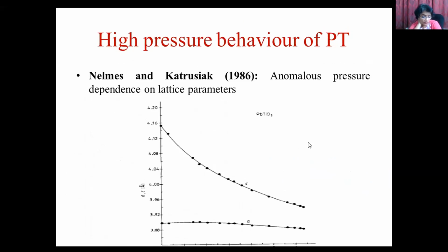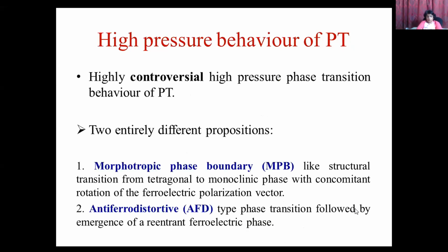There is a study by Nelmes et al. They have found that the lattice parameters show anomalous behavior with increasing pressure, where the C parameter decreases with increasing pressure, while the A parameter first increases and then decreases with increasing pressure.